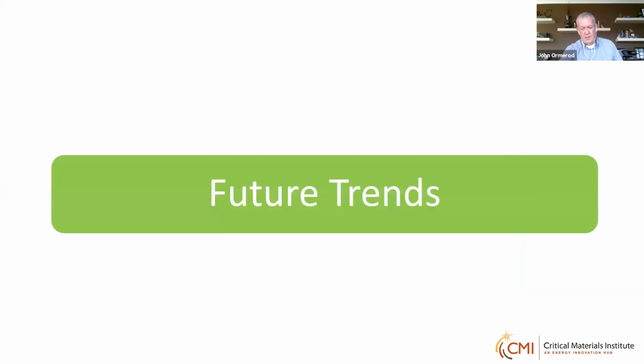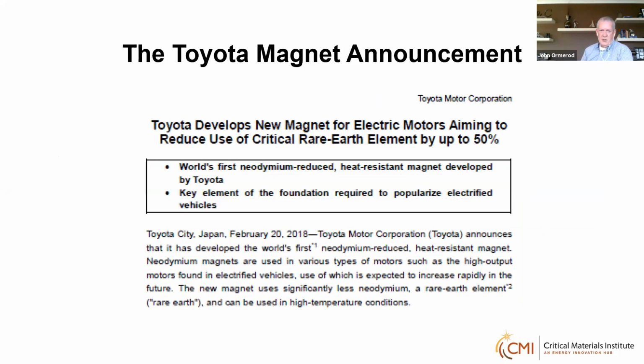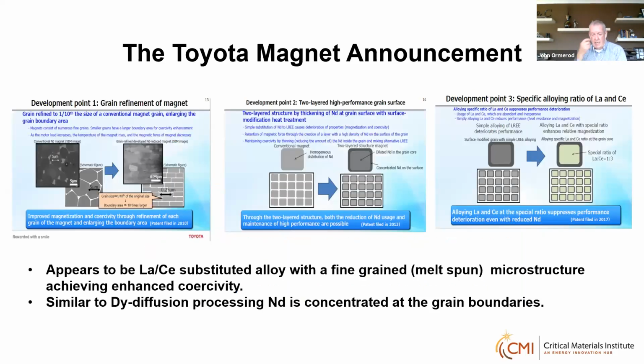Okay, let's move on to a couple of developments that I've received some interest in recently. The first one is an announcement by Toyota. Toyota created a bit of a stir earlier this year when they announced a low neodymium high temperature magnet. Now, there's not a lot of information available, but from what I can glean, it appears that again they're starting with a melt spun process, but it's a lanthanum cerium substituted NdFeB alloy, where it appears they then diffuse neodymium at the grain boundaries to enhance the coercivity and magnetization over the lanthanum cerium alloy. My speculation is they're using hot pressing and hot forming to densify the powders. But once again, there's a limited amount of information available at this time.